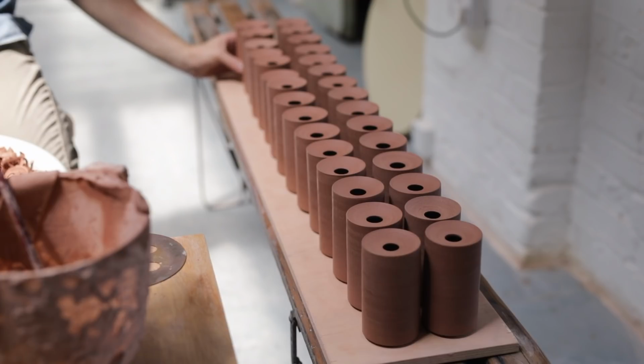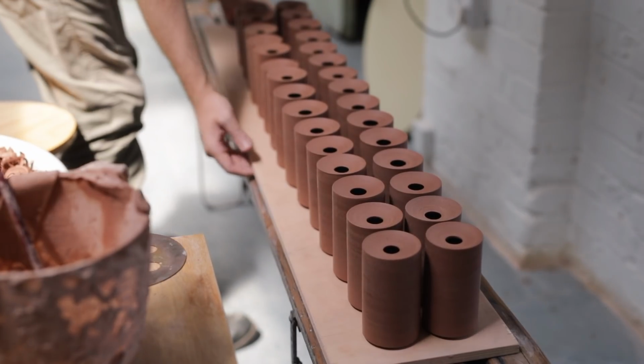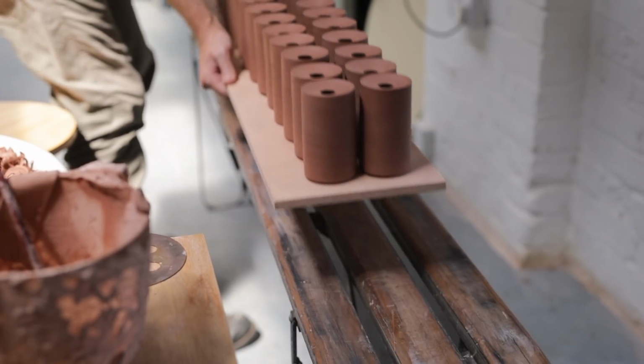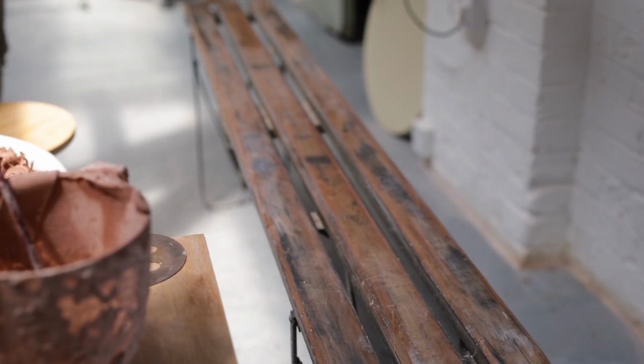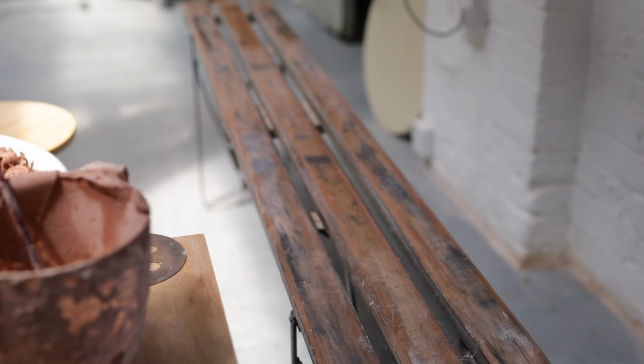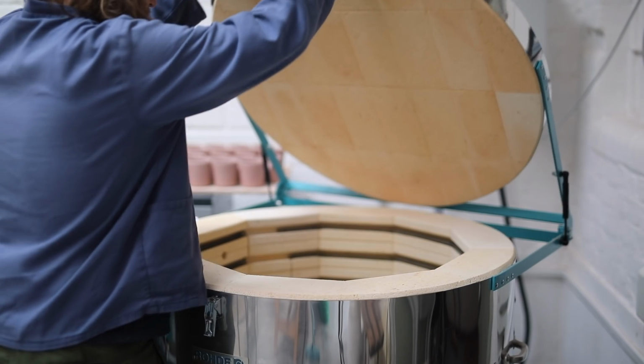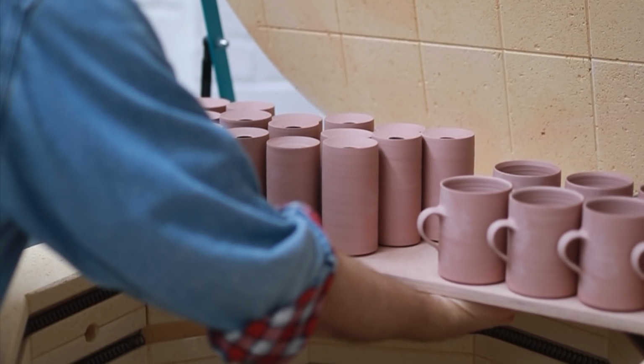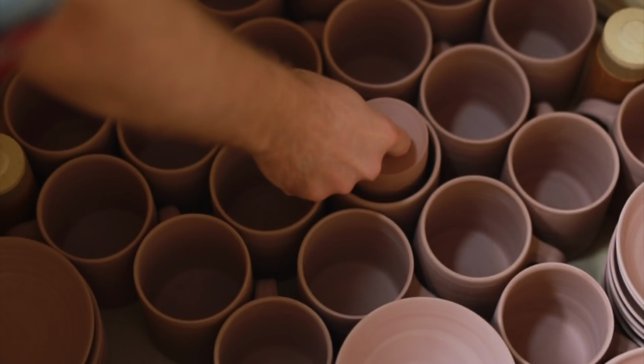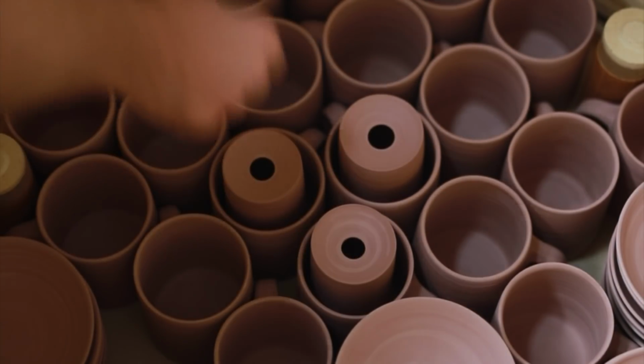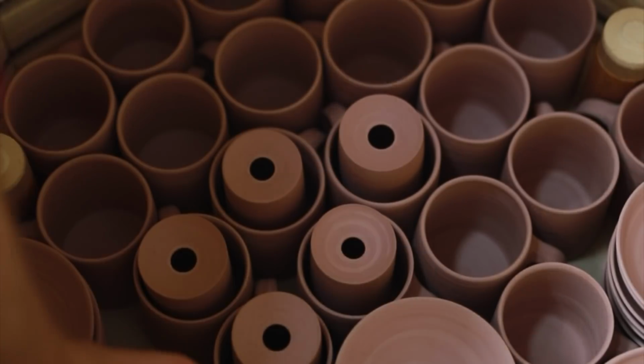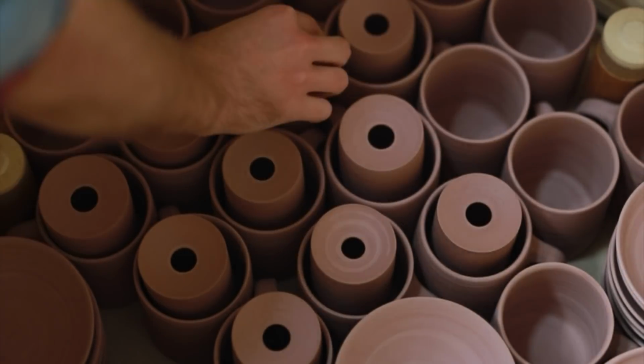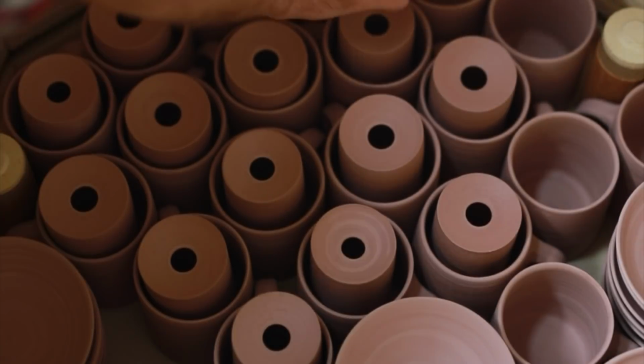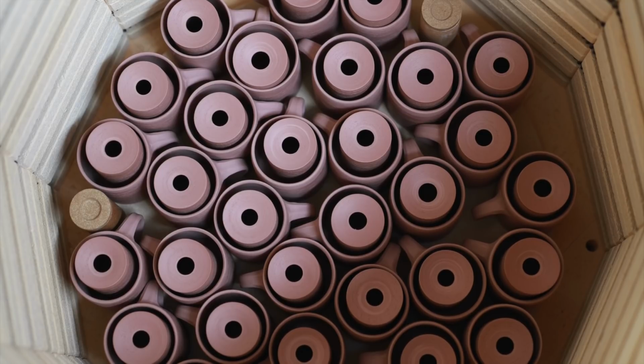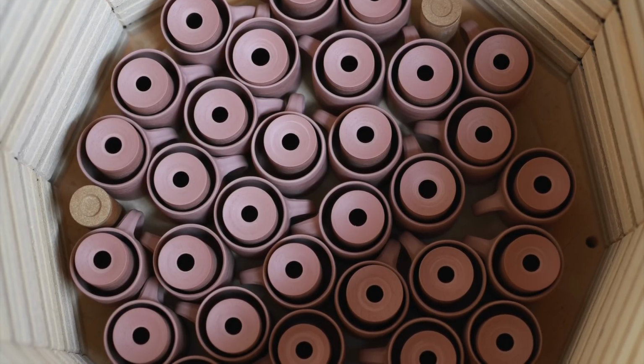Hereafter, I'll let these pots turn completely bone dry, which again, depending on the weather and the studio itself, can take either a day or up to a week. But once they are fully bone dry, I can pack them into my electric kiln to be bisque fired. This changes what is clay into ceramic, a material that's much harder and is now absorbent. I do these firings overnight when the electricity rates are cheaper and the kiln goes to about 1000 degrees centigrade.